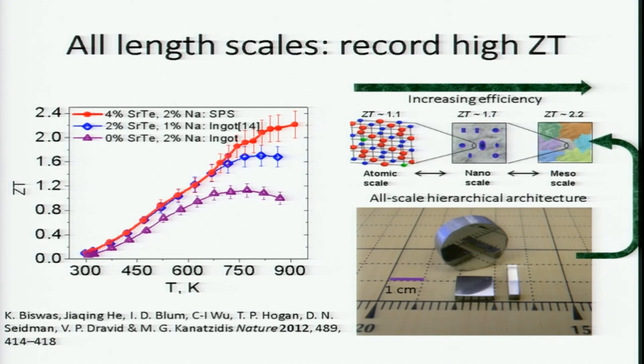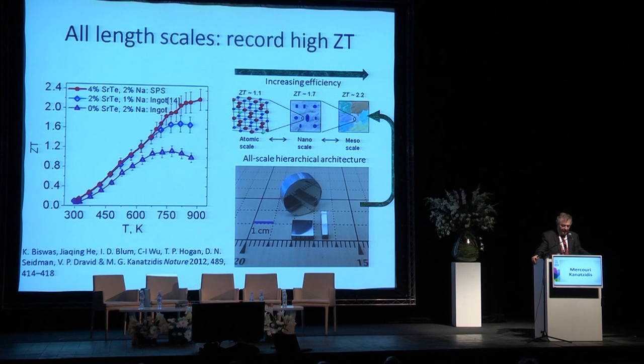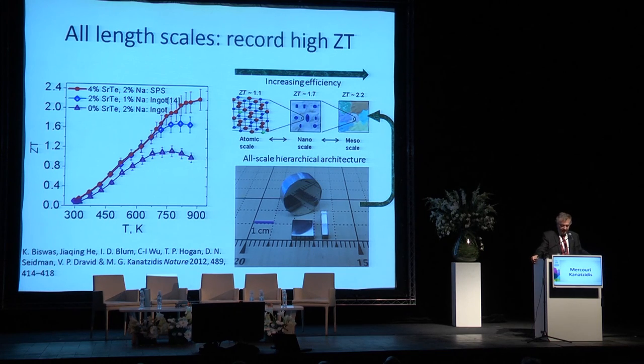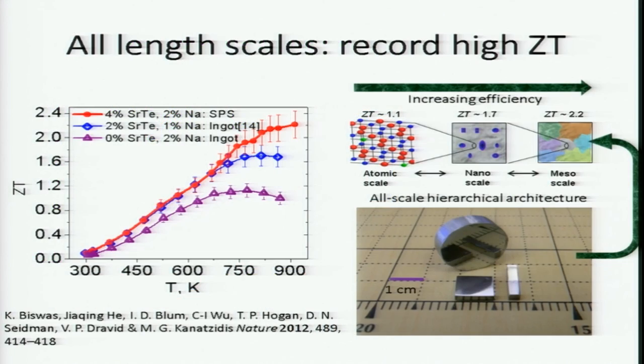So when you do that, then you have another breakthrough in the ZT, and you go up from 1.7 to 2.2. So this is illustrated on the right. If you don't have nanostructuring, you have ZT of 1.1. If you do, you go up to 1.7. Then if you have nano and meso structuring, you go above 2. And that's very exciting. You see the samples over there. This sample is big, it's bulk, it's scalable, but it's a nanomaterial. So that opens the door for scale-up and commercialization.